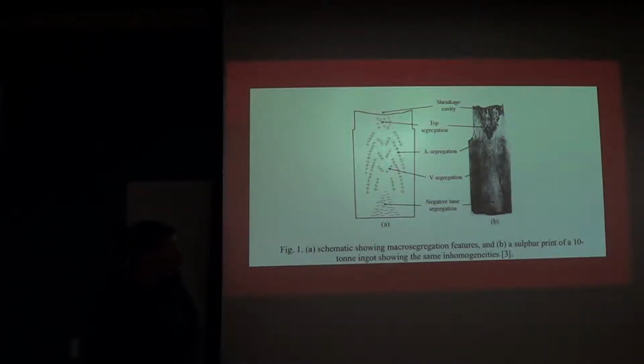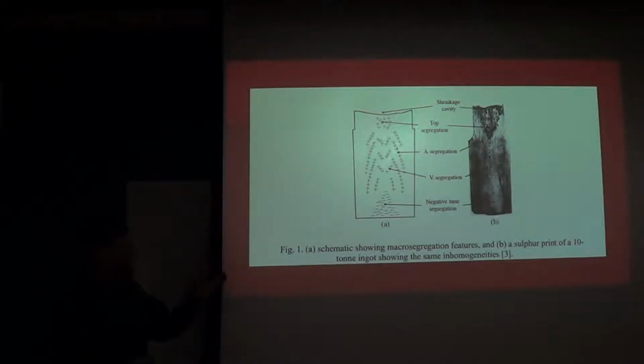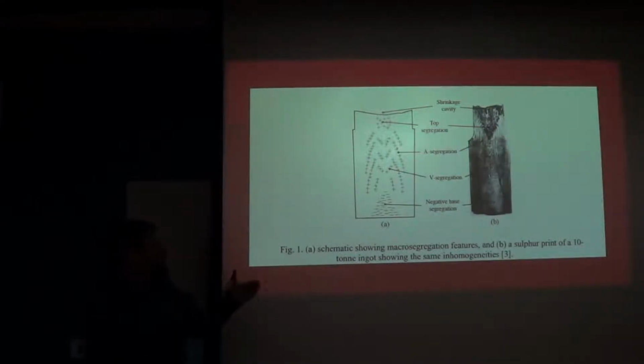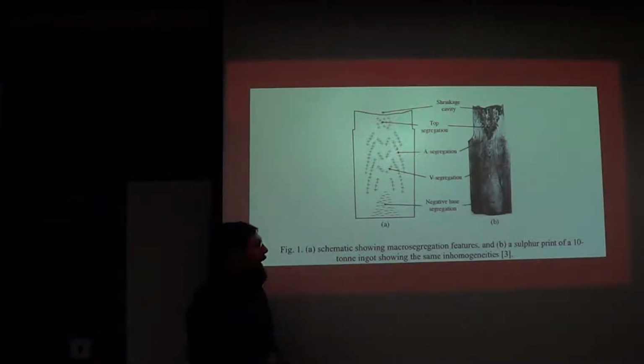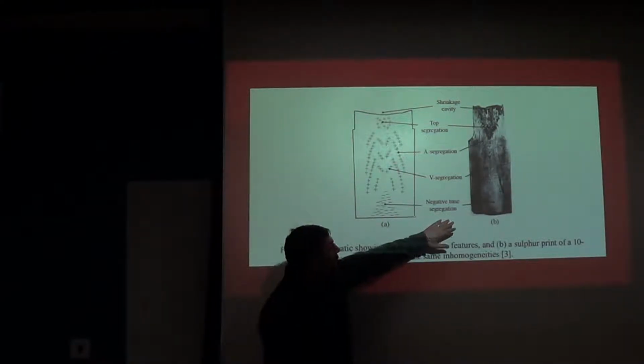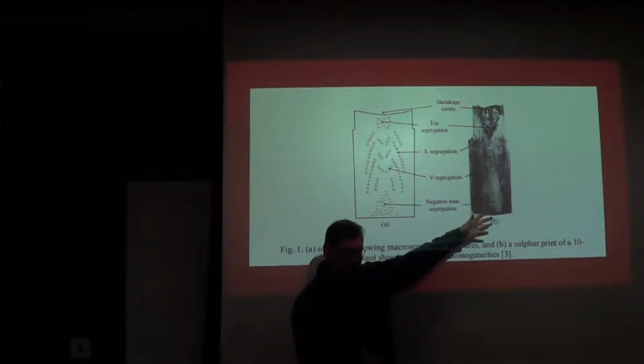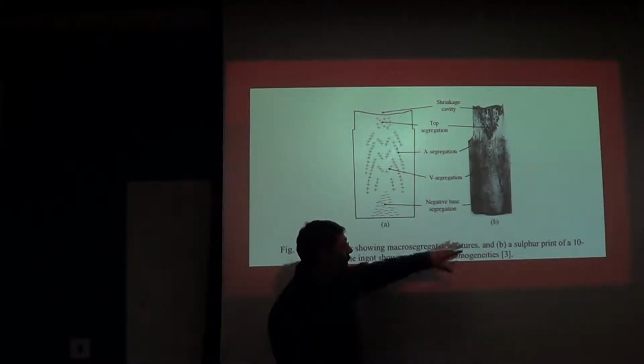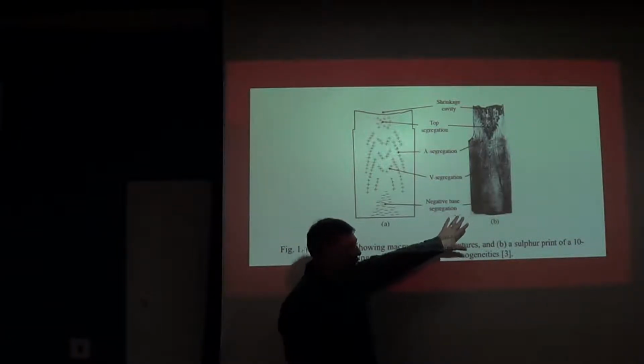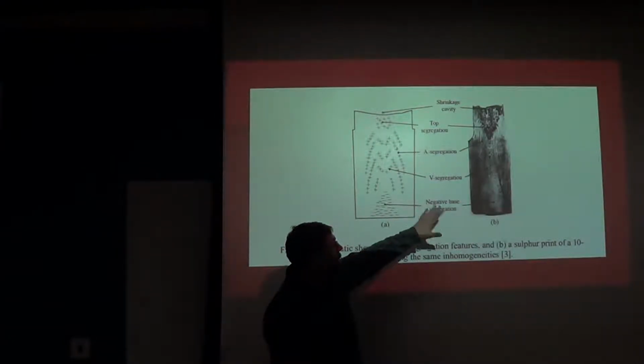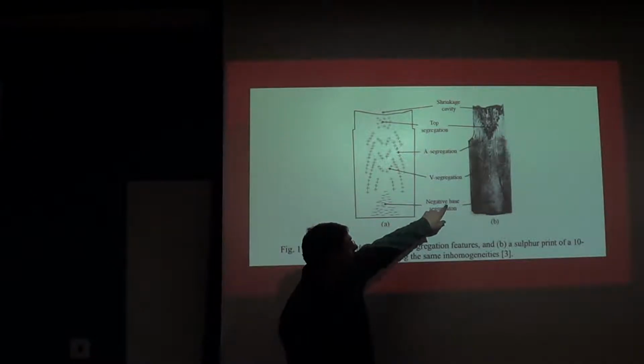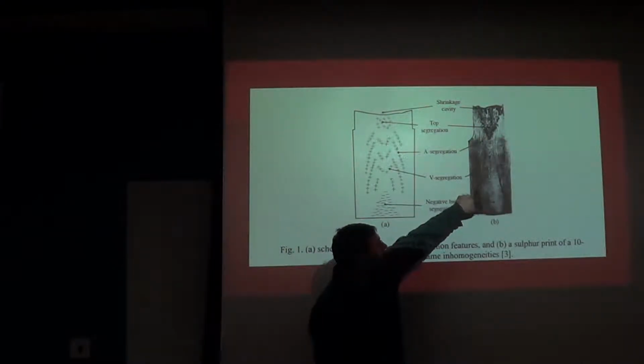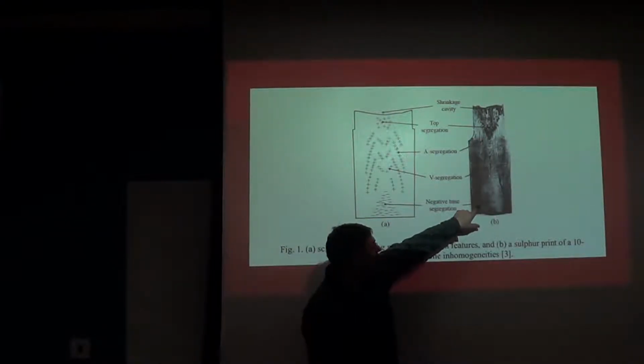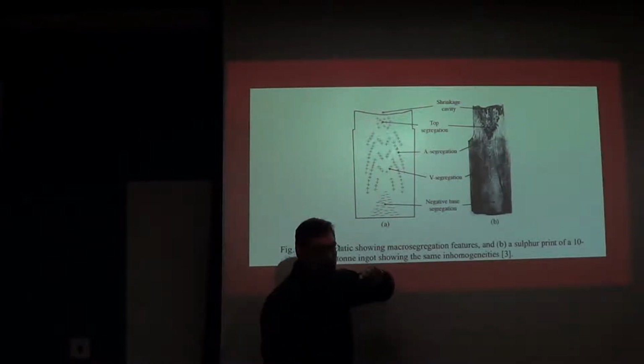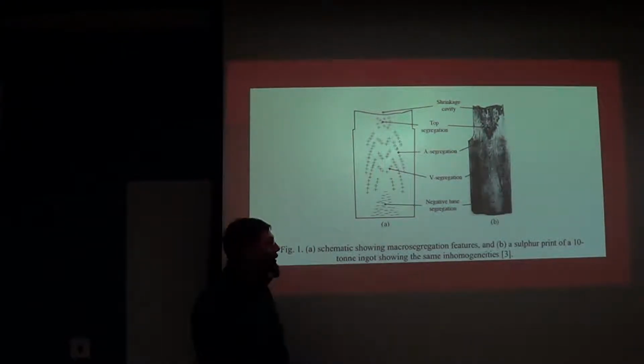Here's an illustration of what that could look like if you took an ingot, sliced it down the middle from top to bottom, and then did a very aggressive etch, what we would call a macro etch. You can see what almost looks like the grain flow that we talked about last week, except there's not been any plastic deformation here. This is just the result of solidification. Because of differences in chemistry, you get this different response to the etching that allows us to see where the segregation is.